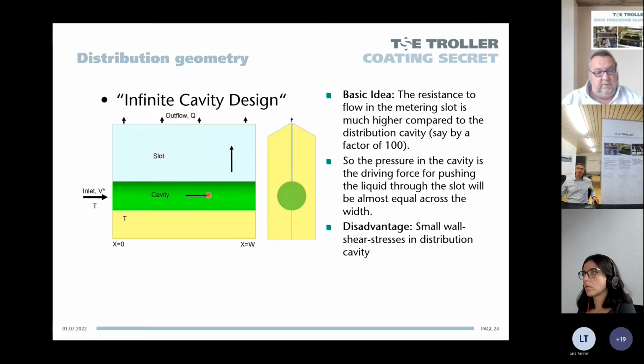However, if you have pigment loaded fluids, especially here in the edge region, there is not enough wall shear stress to move the pigments. The wall shear stress is basically the force close to the wall, which is moving the pigments. And if the pigments are not pushed to move, then they start to settle down and they agglomerate in this region. And this layer is growing and growing and growing.